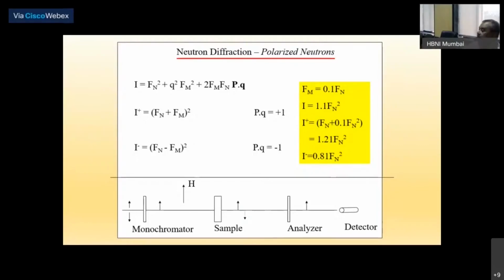See, you have a magnetic structure which is a ferromagnetic lattice. In the ferromagnetic lattice, the periodicity of the magnetic structure is exactly the same as the periodicity of the lattice structure. In that case, if I am below the Curie temperature of that magnetic material, then I will get the Bragg peak due to nuclear scattering, but it will be an increased Bragg peak because I also have the contribution from the magnetic form factor, from the magnetic structure, which is sitting right on top of the nuclear Bragg peak. So it aids the intensity, adds to the intensity.